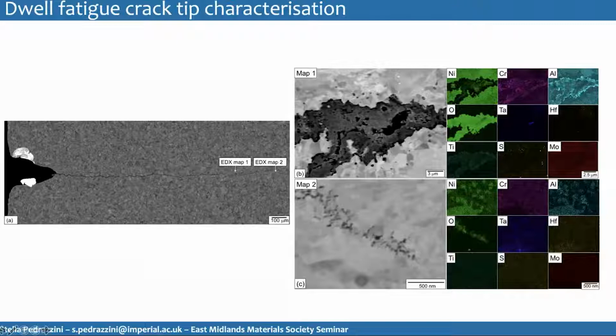you run out of sulfur. So in this case, the salt was applied through a pipette in the notch directly, and we didn't reapply it throughout the test. So at this point, the propagation appears to have switched to a different mode, which seems to be mostly alumina driven. So at one point it stops being corrosion driven and sulfur driven and switches to a bit more oxygen driven.